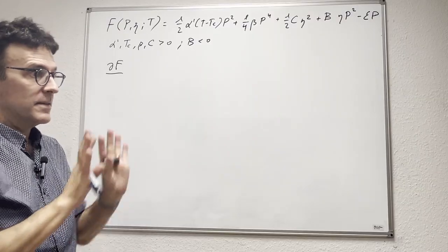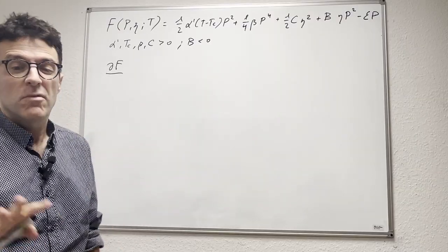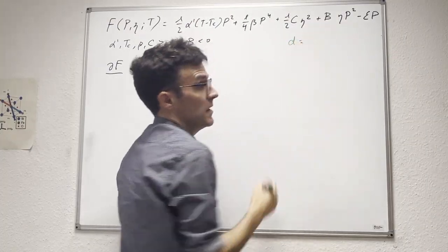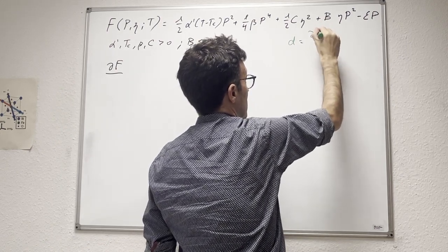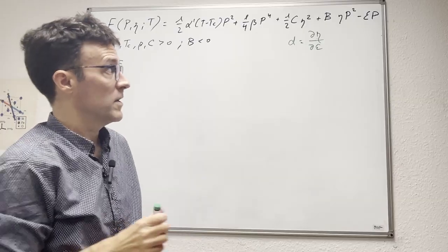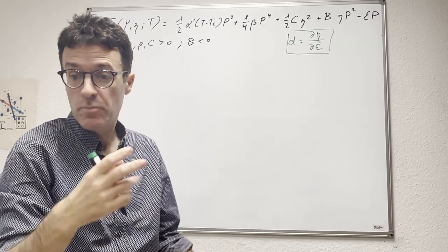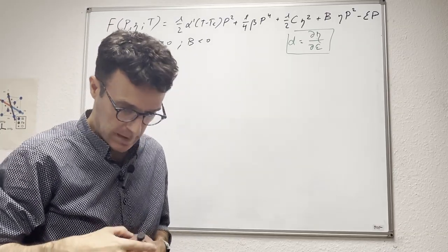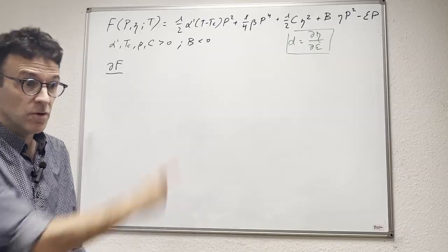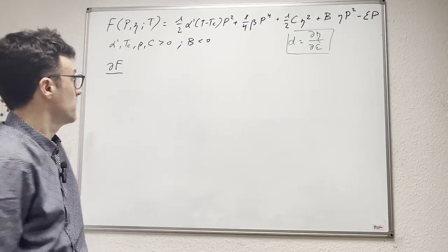In fact, just to state where we are going towards: when I say we want to investigate the piezoelectric response, specifically, I mean that we want to investigate the following piezoelectric coefficient. Typically we call it d, and it will tell us how the strain changes when I change the electric field. Okay, that derivative is the one that we are going to try to evaluate. So obviously, it's a cross coupling between elastic properties and electric properties. There are other piezoelectric coefficients, but those you can learn about in textbooks. We don't have to worry here.